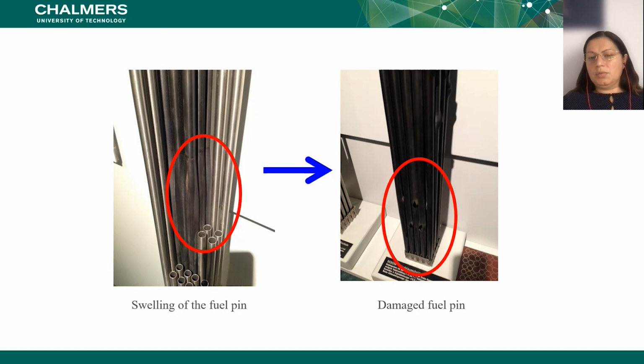So the bubble probably here was either a defect, or you had a difference in temperature because something was stuck on it from the outside. And of course, then you have another temperature inside the tube. So you could see how the accident development can be from the swelling, then you get the release of the fuel. And if you look at the size of these holes here, you can imagine that basically almost a full pellet can be ejected from the cladding. Next, please.